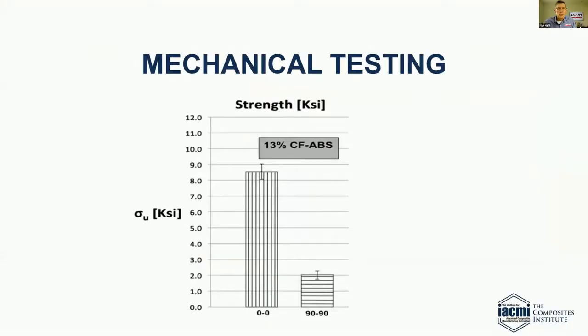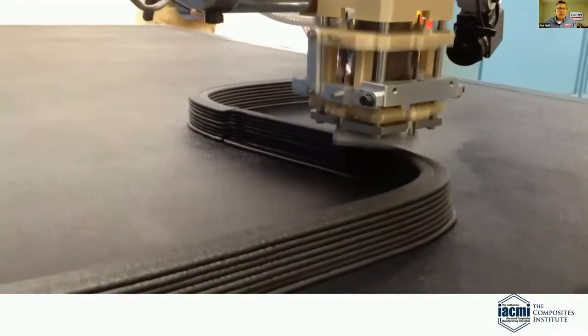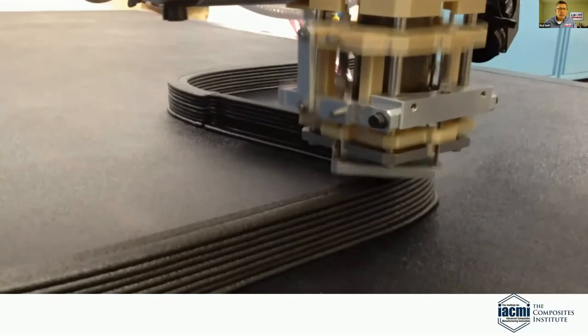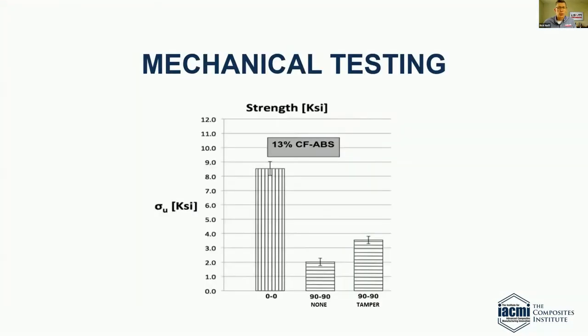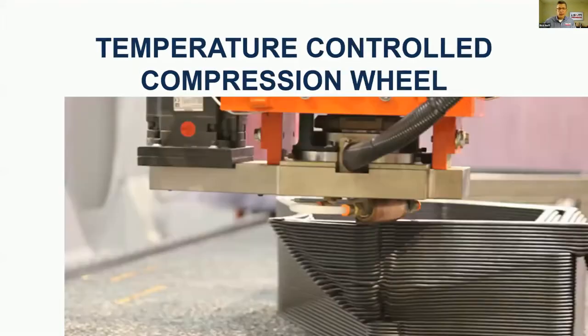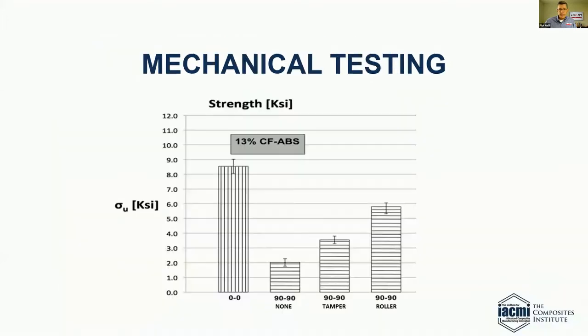Now, when you lay down material just coming out of a nozzle, what you find out is that the strength of the bead is very strong along the bead because the fibers all line up that direction. But the layer-to-layer bonding isn't all that good. The strength, if you pull it in the Z direction, is not too strong. Now, Oak Ridge had a partial solution to that by using a tamper that tamped the material down and improved the layer-to-layer bonding by a considerable amount. But what we see today is that the leading technology is a temperature-controlled compression wheel that THERMWOOD employs. And that really improves the layer-to-layer bonding to the point where you're very close to the strength of the thermoplastic material itself without the fibers in it.